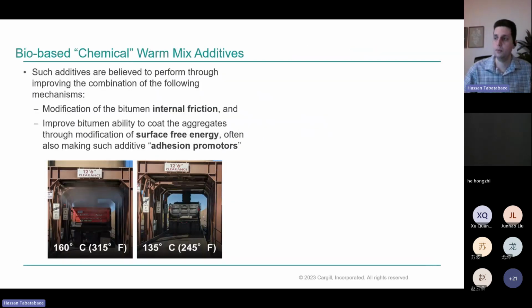So when we talk about chemical warm mix additives, these are additives that are believed to perform by modifying the internal friction in a bitumen film, which allows for the better movement of aggregates and workability and compactability. They also, as a byproduct of that impact, often work as wetting agents. They modify the surface energy and surface tension of an asphalt binder and the bond characteristics on the interface between bitumen and aggregate, and can help as adhesion promoters.